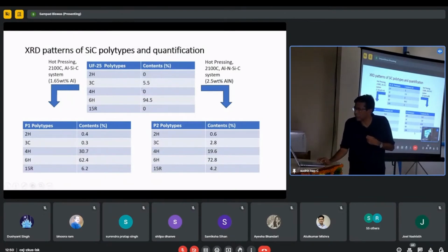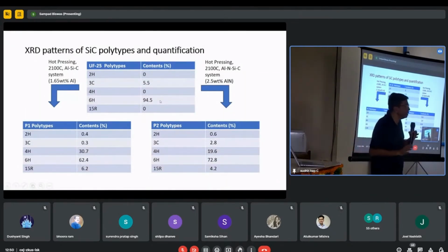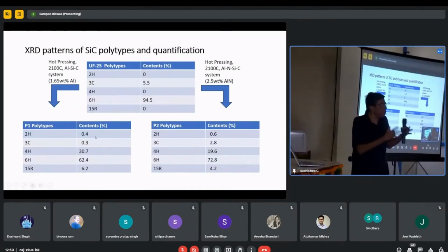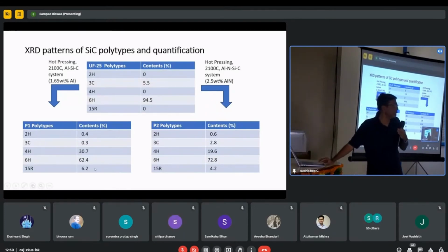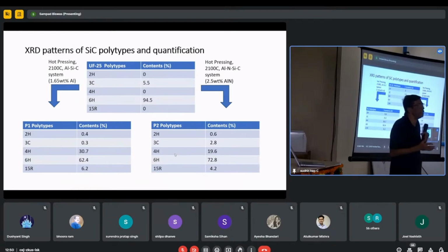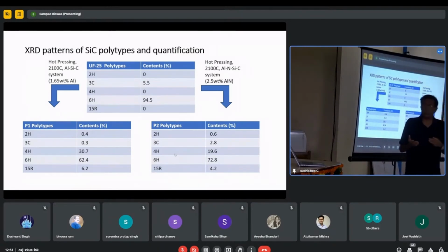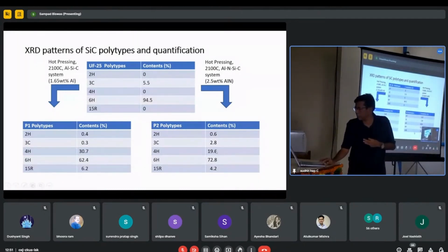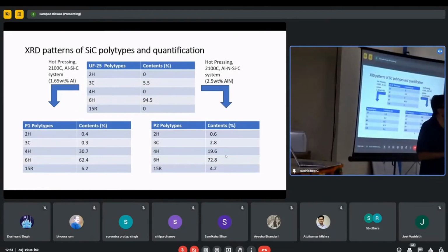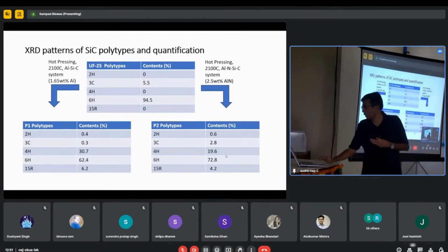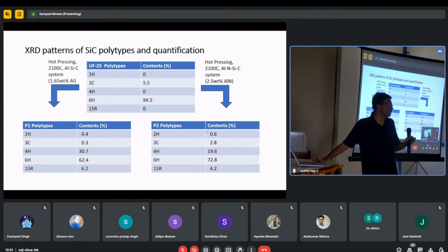So, what we have taken is the starting powder. If you look at the composition, you can find the 3C content is only 5.5. Mostly it is 6H powder, so we started with the 6H powders. Now, when we prepared the ceramics after sintering or hot pressing, we found that the quantity of 6H is reduced while the quantity of 4H has increased. This is possible due to a polytypic transformation from the 6H structure to the 4H. And in some cases where you add a different additive, you find that your polytype ratios change. In the P2 samples, mostly the 6H variety is maintained, and very little transformation to 4H and 3C occurs. This is the original ceramics I am talking about. Then I will show you how it changes after the impact with the bullet.